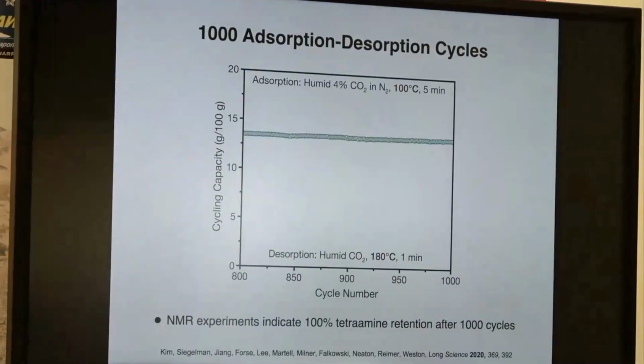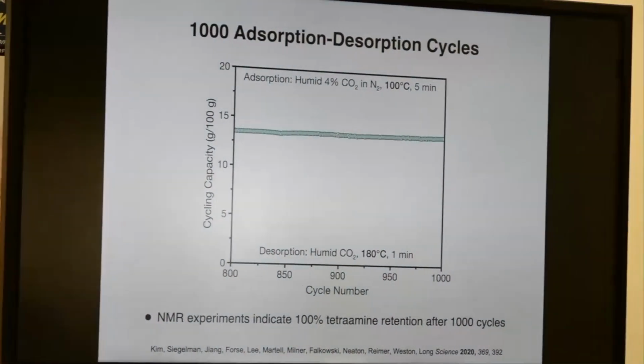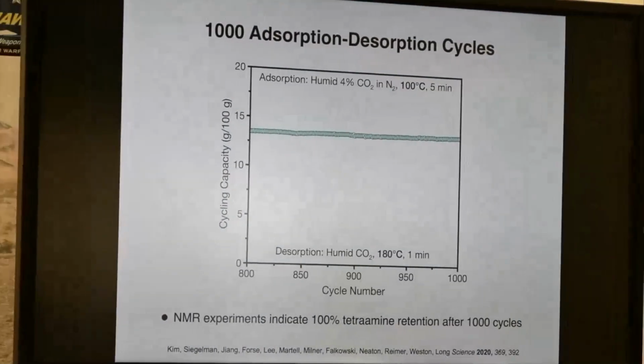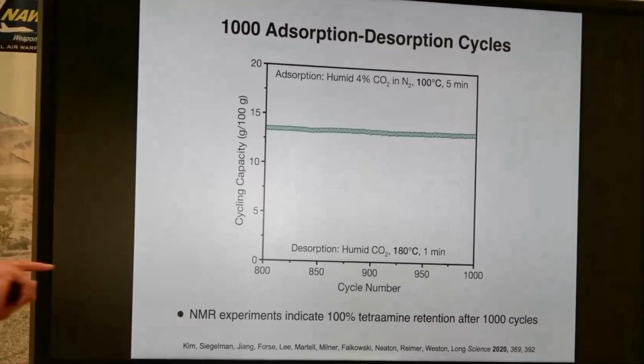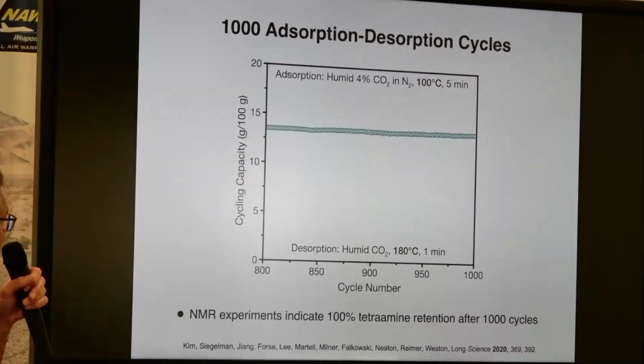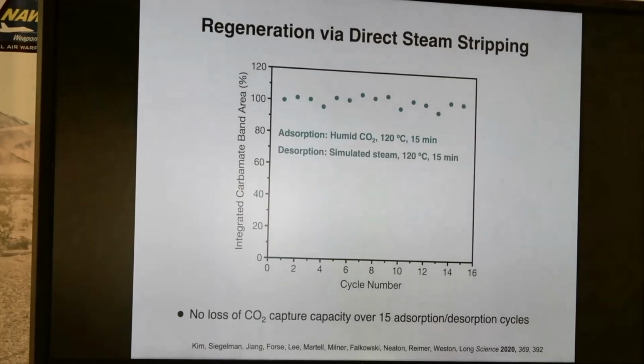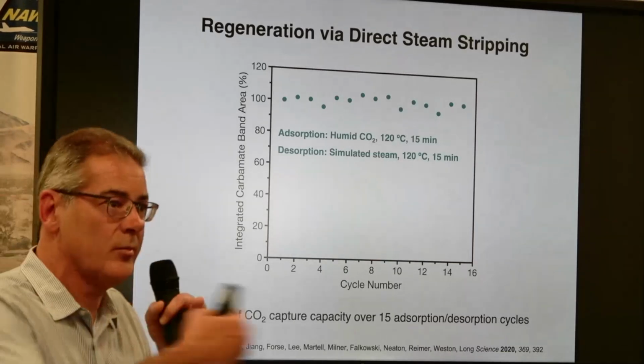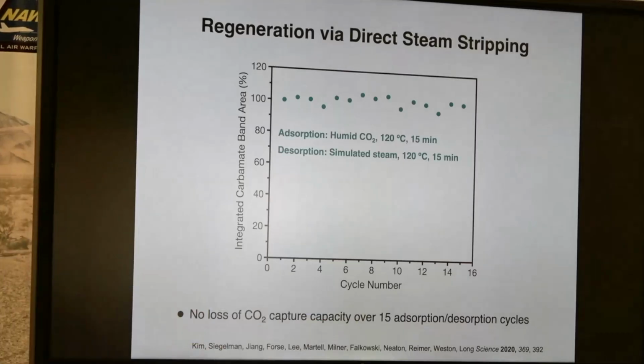And it does cooperative CO2 uptake now by design at high temperature. So here we're capturing at 100 degrees C and desorbing at 180 without any loss of capacity. So that made us curious, could we just direct steam contact these? A lot of power plants could have some source of steam, and steam stripping could be a very effective way of regenerating and releasing the CO2. So these are robust to direct contact, which is very aggressive to expose materials to.